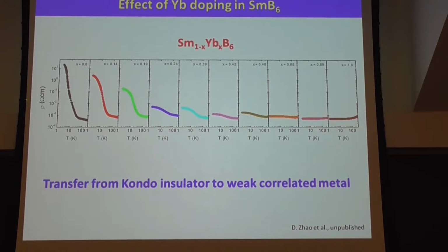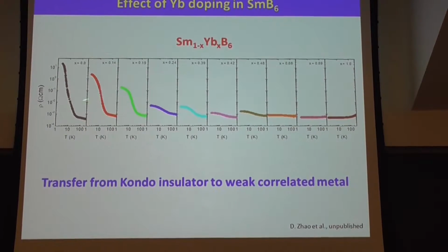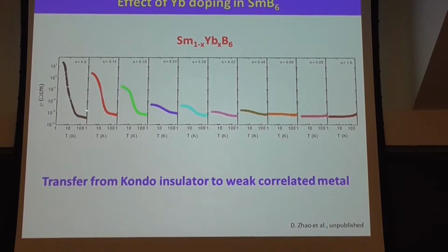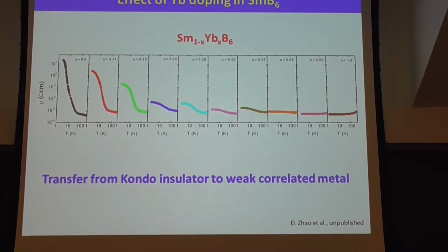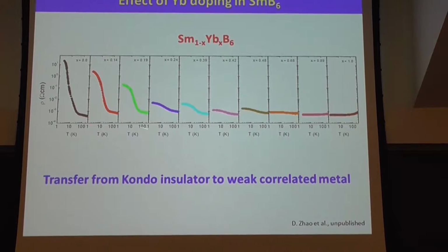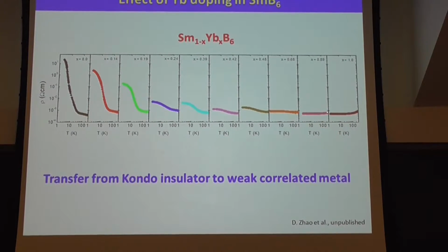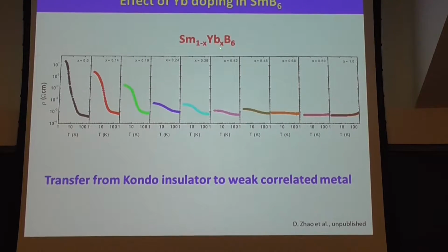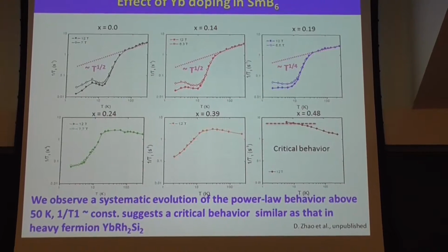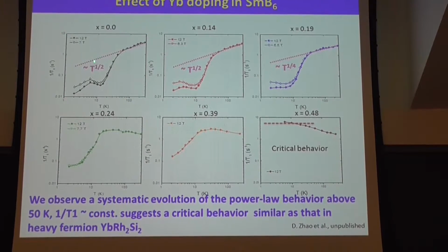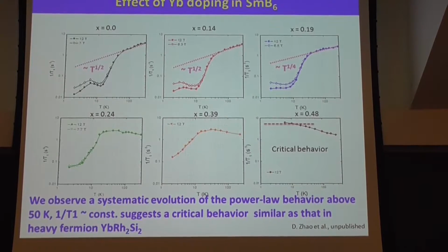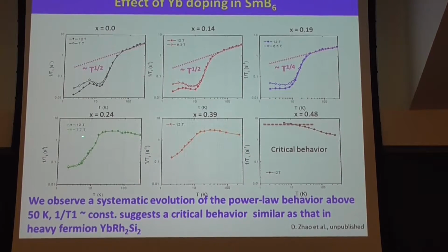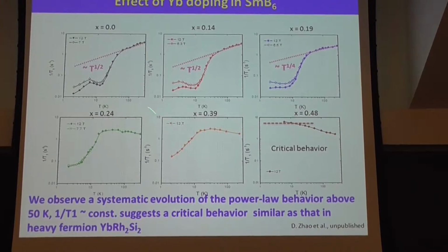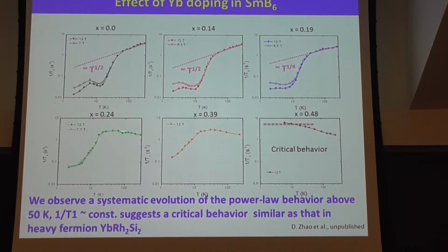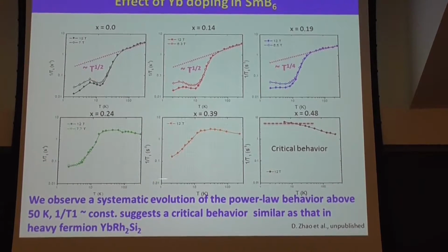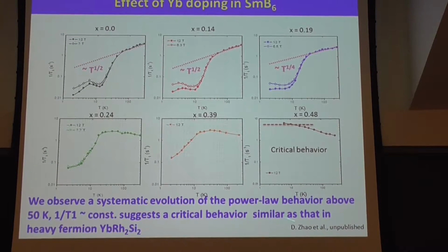Also for resistivity as a function of this X, you can see from the very low doping it still shows some insulating behavior and also the topological surface state. But from here to here it goes from a Kondo insulator to a weakly correlated metal. This is for the Yb-doped SmB6, which is a metal. And we do the NMR measurement. Before I just showed you this data, but it's very interesting for the higher Yb doping. You can see here it shows the 1 over T1 is, above 50 Kelvin, almost constant. This suggests critical behavior, similar to the heavy fermion material.